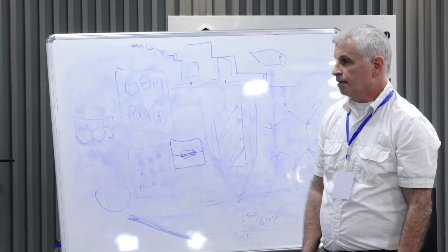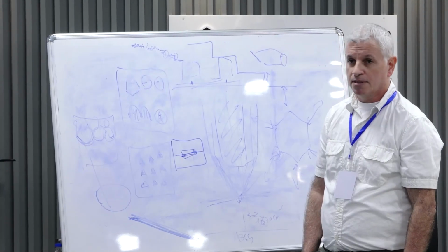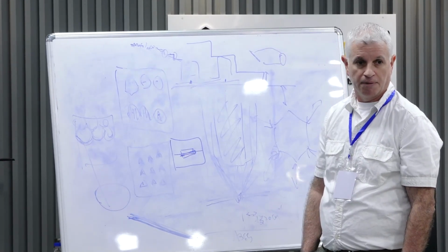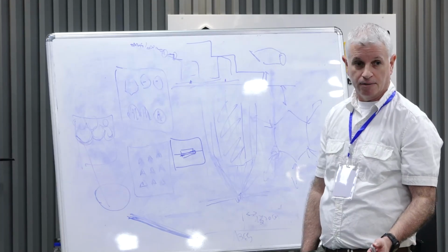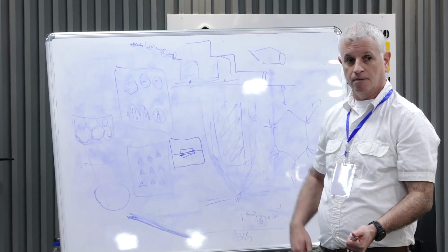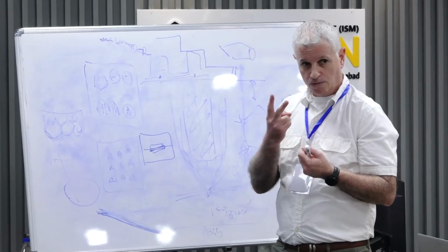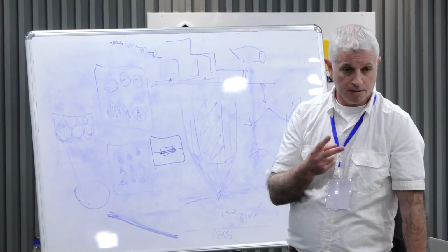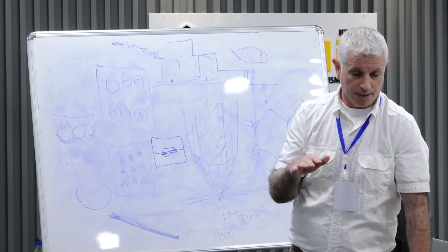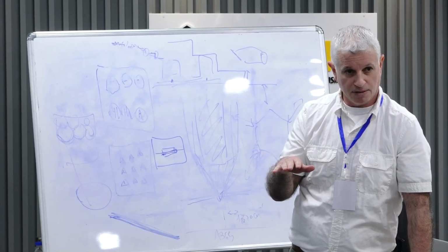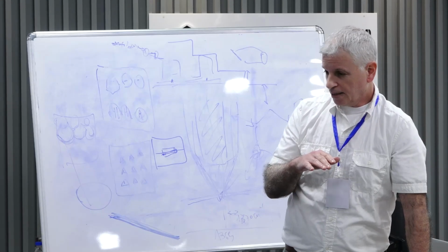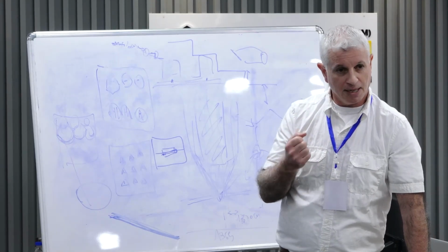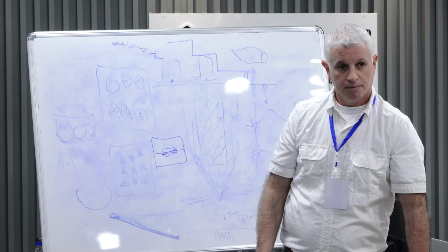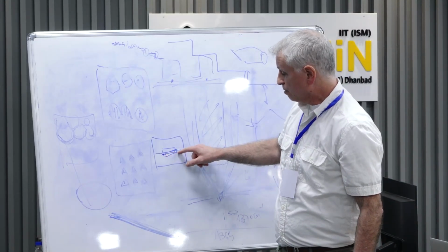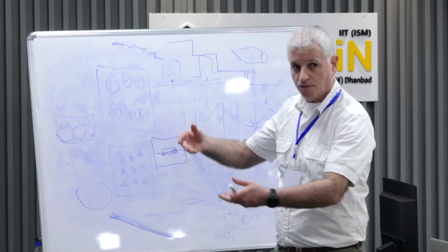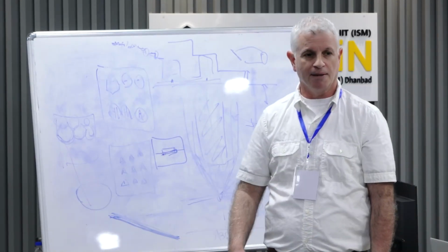It will be tens of, I would say, 100 nanometers, maybe more. That's why you have a protective layer. You deposit the protective layer. It has two main reasons. One is to protect the layer from a lot of things that happen on the surface, and also it gives rigidity and mechanical support to the lamella. Basically, because you also have the part of the substrate. I don't know exactly what the minimum thickness is.